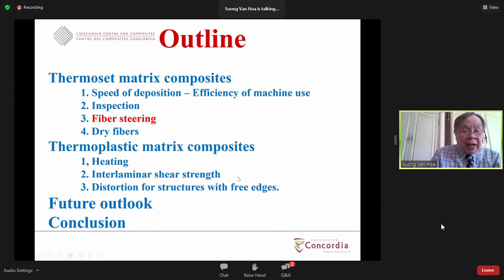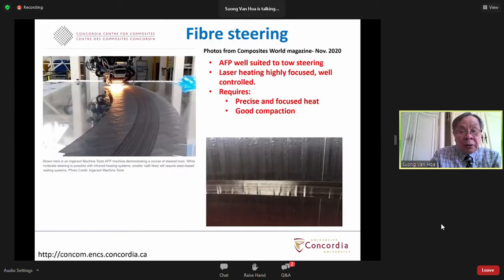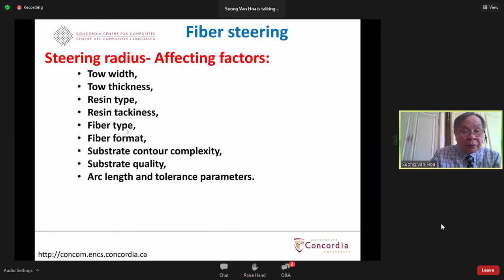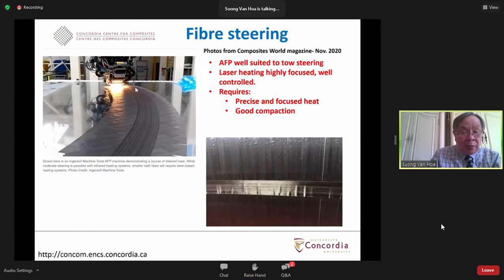So the next aspect concerning AFP is fiber steering. Certainly one of the nice features of automated fiber placement is that it can steer the fiber. There was also work done at Bristol some time ago about tow shearing, which is a similar approach to match curvilinear fibers. However, there is a minimum radius that you can steer, because if you steer below it, you get defects such as buckling and wrinkling.